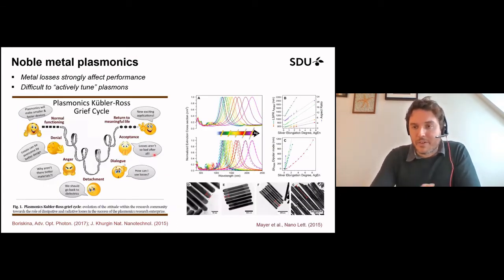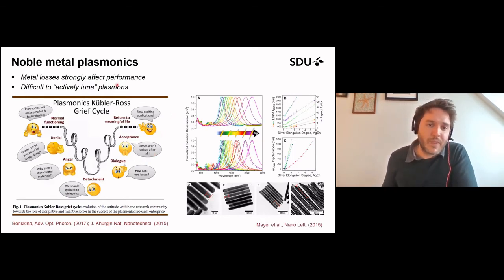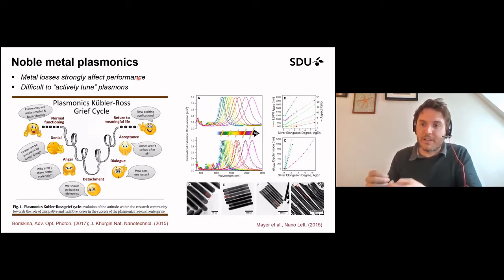Now, there, of course, are a few disadvantages to plasmons, and I'll mention them here. In noble metals in particular, which are being widely used for plasmonics, you have intrinsic losses, right? When the electrons are moving around in the metal, they're going to scatter with each other, with impurities, with the ions of the lattice in the crystal. And these losses can really diminish the performance of your device. You want the plasmon to oscillate strongly with the light, and you don't want it to lose its energy or decohere very quickly. But unfortunately, this is what's happening.